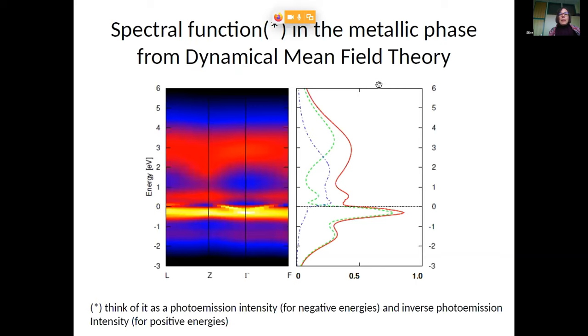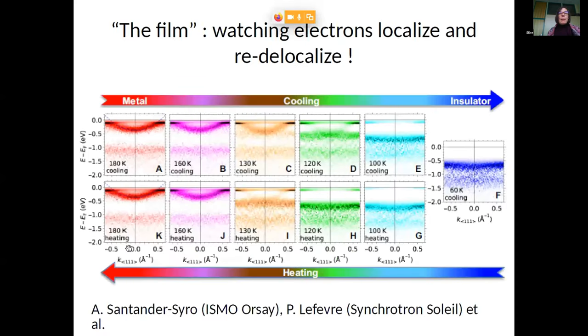So here you have it in pictures. You have here an A1G band just poking over the Fermi level, and then you have EG pi states making up all the spectral weight down here and being close to half filled. Now the beautiful thing that came about was that in the group of Andres Santander Syro and Patrick Lefèvre from Synchrotron Soleil and Orsay, they could measure with angle resolved photoemission as a function of temperature. That means really going through how the states evolve when you cool down and when you heat up again.